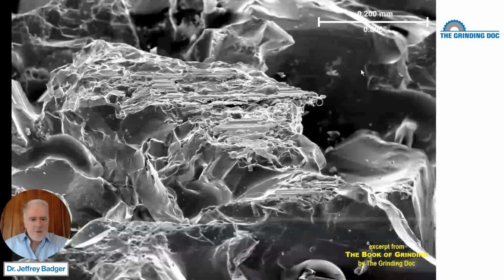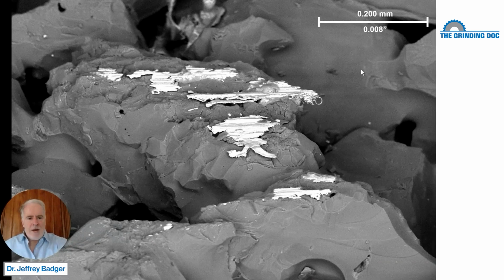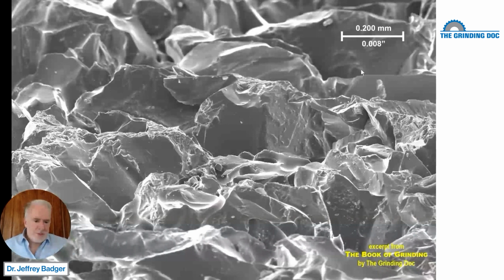All right, here's a different one. So here is a picture of an aluminum oxide wheel that's been dressed dull, and what we have is smeared steel. Turn on the backscatter and boom, look at that. Nasty and unpleasant. We don't want to grind with that. That wheel was dressed dull, and when it was dressed dull, it loaded very quickly. Here's a wheel that was not dressed dull. This is a wheel that was dressed relatively sharp, and what happened? We didn't get any loading. Or let's say we got loading very, very slowly because we dressed the wheel sharp.